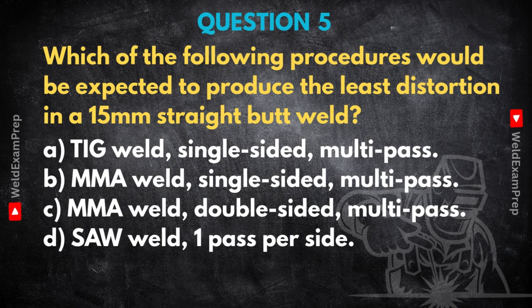Okay, minimizing distortion in a reasonably thick butt weld. Considering these options, the procedure expected to produce the least distortion is D, SAW weld, one pass per side, submerged arc welding. Interesting. That might seem counterintuitive to some. SAW puts a lot of heat with those big single passes, right? Wouldn't more heat mean more distortion?